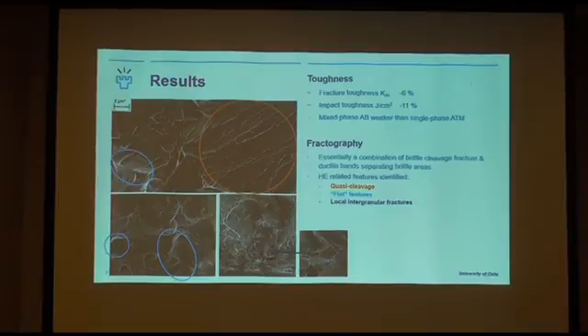But we are also able to identify hydrogen embrittlement related features throughout the fracture surfaces. So we have classic cleavage, flat features, and also local intergranular fractures. So here we have these lath-like or lath-sized features on these flat areas, and then in this example we have a cleavage fracture propagated that is indicated in this local intergranular fracture.